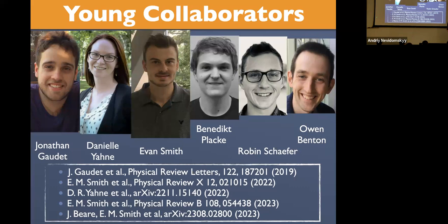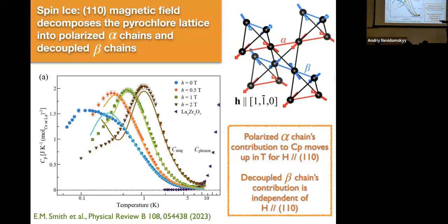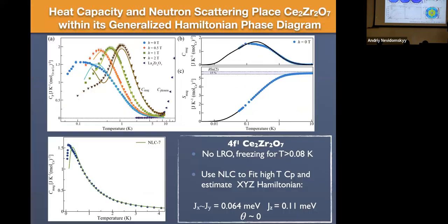Oh, so it's basically, right, you mean just the fact that it goes up and comes down? Yeah. So it has to come down. It's got to eventually go to 0, and so this is maybe a better picture to look at here. It's all the same data. Everything in blue is the same, and this is the fit to the theory that I was talking about before. And then down here we've got an extrapolation of the heat capacity to go down to 0, which it has to do because the integral of C mag over T from 0 to T is the entropy as a function of T. And when we get up to high temperatures, that's got to give us R log 2 because that's the number of degrees of freedom that you have in the ground state.